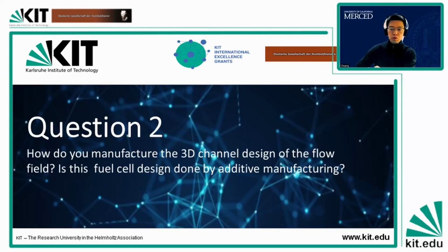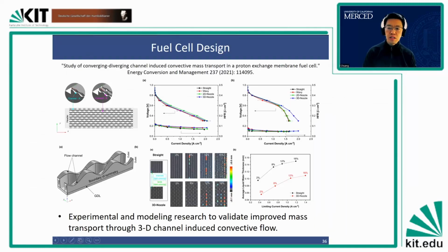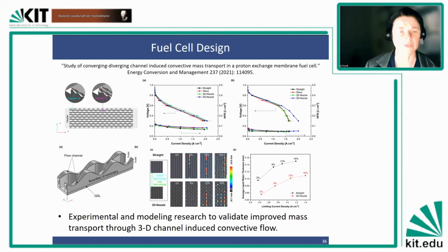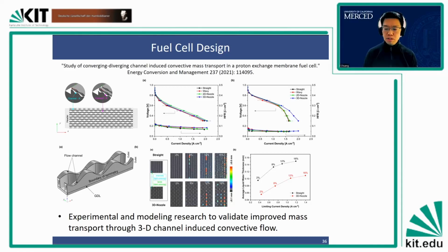This material, when we manufacture it, the features that you see here range between about 330 micron and about 660 micron. We use a resin impregnated graphite plate, and we use a milling, machining process to do this. But you ask a critical question. Right now we have an active project on additive manufacturing, 3D printing, and lithography to design a pattern feature to be able to control transport properties. This is something that we are actively doing now. We don't have significant results in this area, but this is an area that we are actively pursuing.